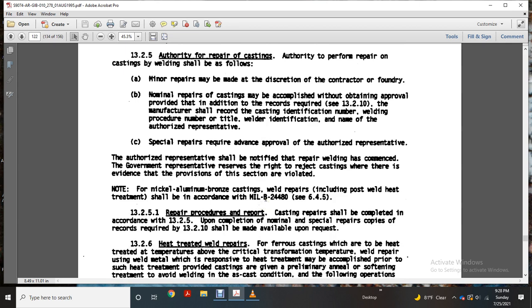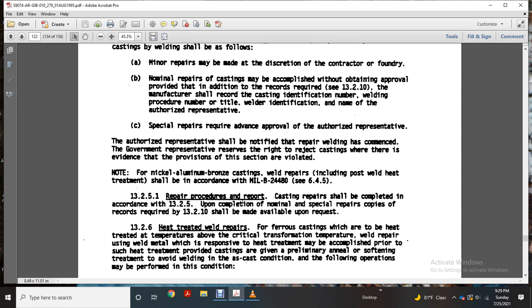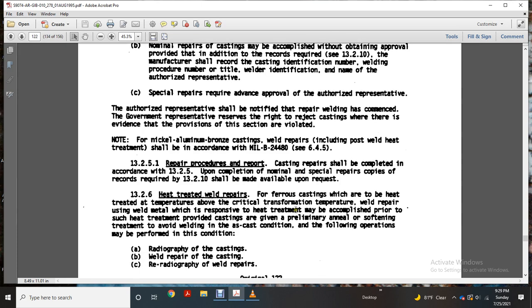The government representative should reserve the right to reject the casting if there is evidence that the provision in this section is violated. No nickel alloy bronze casting welding repairs include post-weld heat treatment, which shall be in accordance with MIL-B-24480C, section C4645. 13.2.5.1 Repair procedure and report. Casting repairs shall be completed in accordance with 13.2.5. Upon completion of nominal and special repairs, copies of records required in 13.2.10 shall be made available upon request.